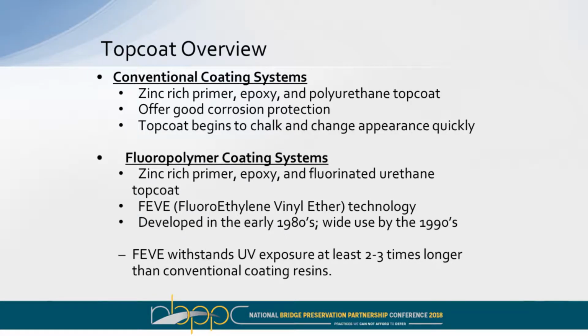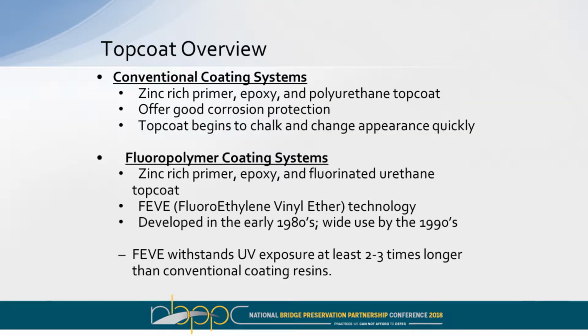So conventional coatings, most people think of a three-coat system when they're painting a bridge: a zinc primer, epoxy middle coat, and a polyurethane top coat. These do offer good corrosion protection, but the top coat can start to change in appearance and start chalking and fading relatively quickly. Fluoropolymer coating systems use the same three coats. There's nothing changed about the primer and the middle coat.